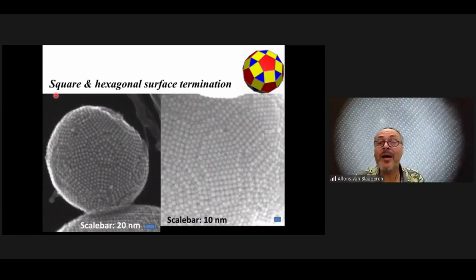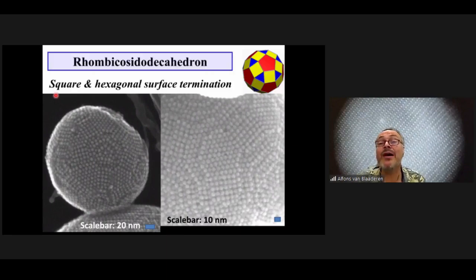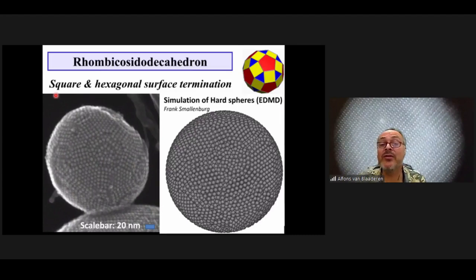When we saw this happen with different nanoparticles, we weren't sure whether the attractions played a role or not. So we did it with micron-sized particles. We had to do it very, very slowly, but then we saw the same structure. So then we started doing computer simulations on this, and we found still the same icosahedral structures.